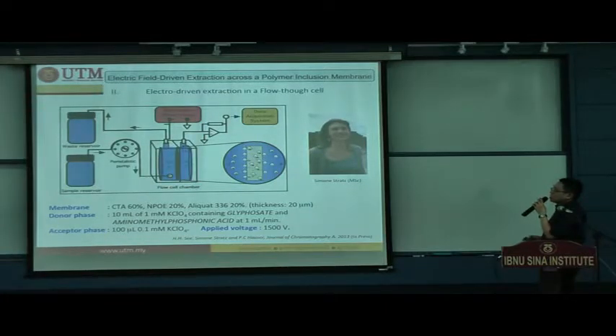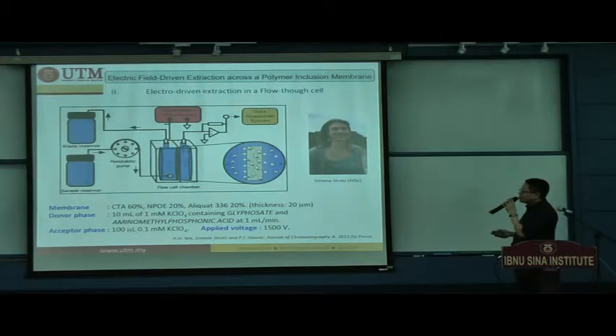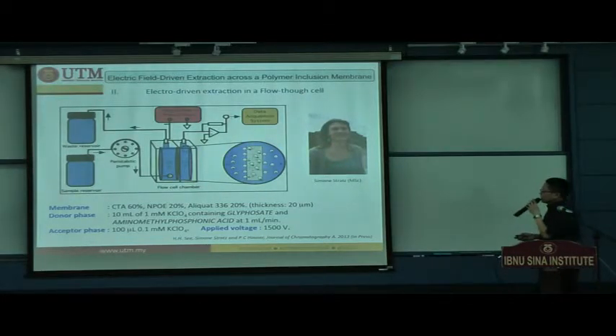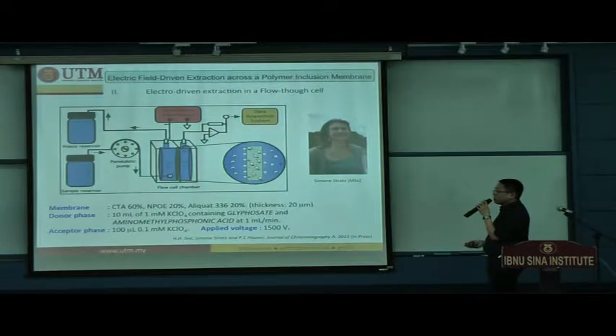The sample solution is now continuously pumped into the donor phase chamber, and the voltage is applied continuously for the extractions. So right now you can pump in as much sample solution as you want, but still maintain 100 microliters of acceptor volume, which means you are enlarging the enrichment factor because of the sample to acceptor volume ratio. In this project, she focused on detecting two analytes, glyphosate and its major metabolite, aminomethylphosphonic acid. The sample is 10 milliliters, and the flow rate is set at 1 milliliter per minute, which is 10 minutes of extraction.